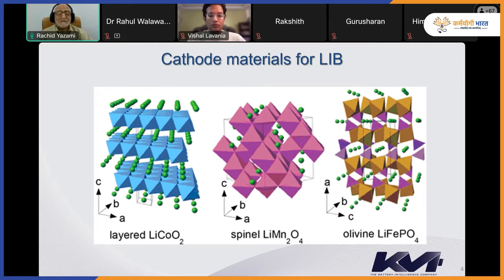Okay, so a battery based on lithium iron phosphate has an energy density lower than 200 watt hour per kg, whereas batteries based on layered structure oxide can go higher than 250, even 270 or 280 watt hour per kg. And this is where a lot of work is currently carried out to increase the energy density, and hopefully in maybe the next 4 or 5 years we will hear of batteries where energy density is exceeding 300 watt hour per kg, and the cathode material will be one of the components that will improve the energy density of the battery. Next slide, please.